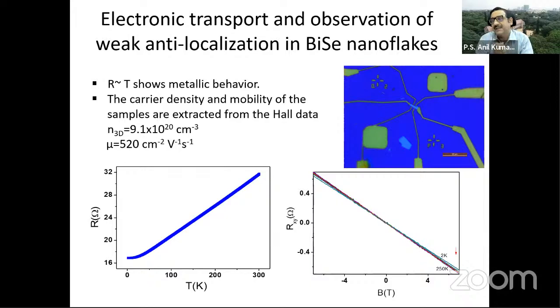So we wanted something like that, but unfortunately, though I said that the bulk is insulating and the surface is metallic, here the bulk is also kind of conducting because of the self-doping, because of this deficiency of selenium in the sample. But nevertheless, we have this crystal, let us understand. Because of the self-doping, it gives a very high carrier concentration, and the mobility is of the order of 520, which we obtain from the Hall effect measurement in these samples.